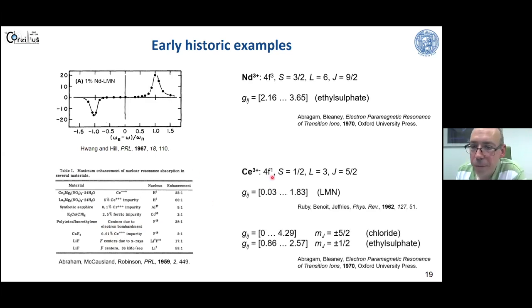For example, if you look at the cerium, this is now a case where we can have tremendous ranges of our effective g factor between 0 practically and 1.8 in one system. And then in other systems, it actually depends on which Kramers doublet practically in this total angular momentum the ground state is. You can here have then very different effective g tensors in the end. And this is just to demonstrate how complicated the systems become if you have significant orbital momentum in your ions.